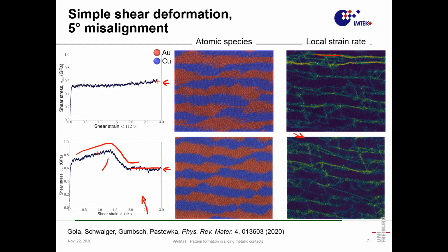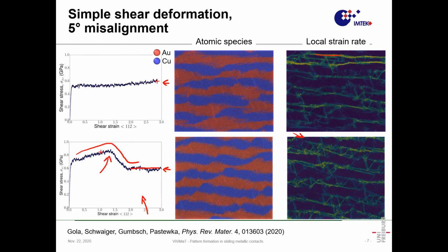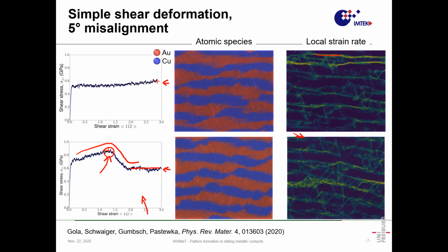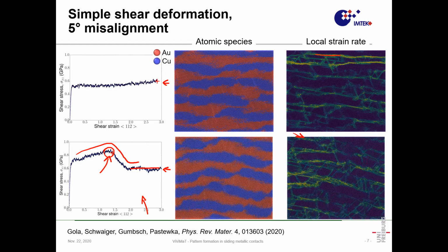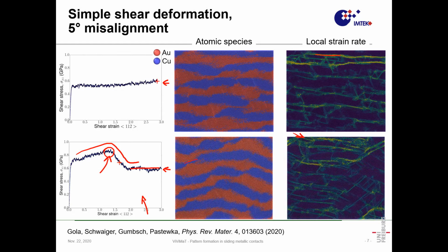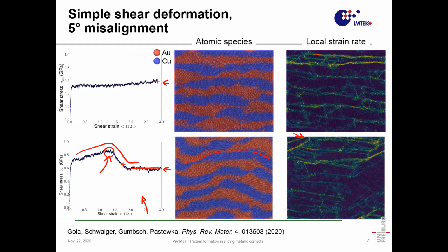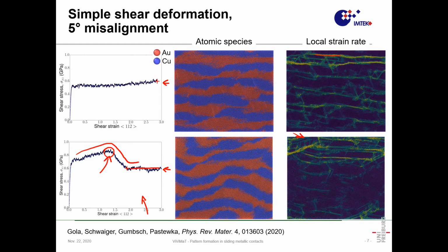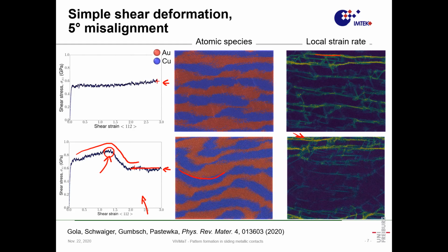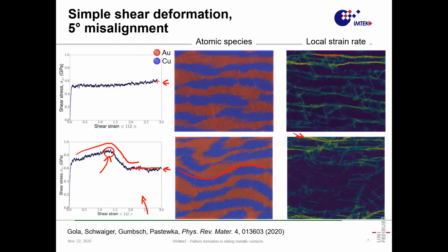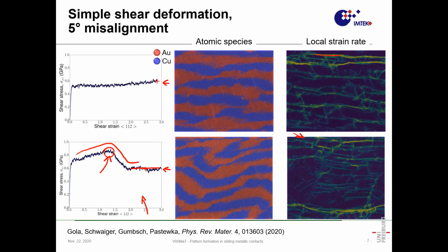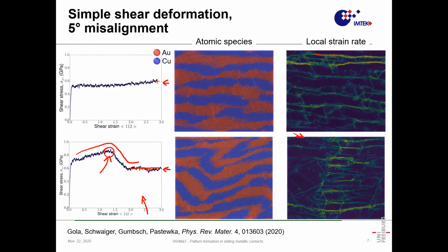But the interesting point is when our calculation hits this point of instability up here, which is going to happen about now. And what you start seeing now is the occurrence of waviness. There's sort of a wave that starts developing in the interface of our system. You see here clearly this waviness that the experiment has also shown, that I've shown you before. So in order to stabilize this, we need this lattice tilt and we need the initial interface roughness.